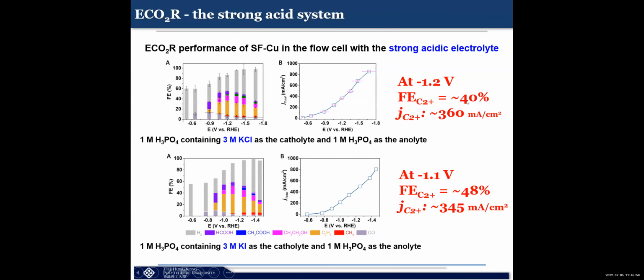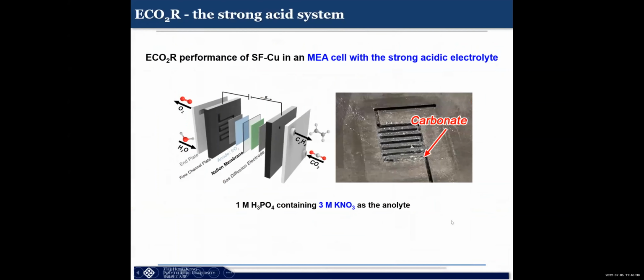So for the C2, we can get about 40% at minus 1.2 volt. For this condition, 1M H3PO4 with 3M KI, basically the same as the work for the strong acidic environment, we can get about 48%. So in terms of the catalyst itself, the C2 Faraday efficiency is already better than the Sargent group. But the problem is if we are using acidic electrolytes, the MEA is not going to work because of the membrane. So this process is very difficult to actually make practical.